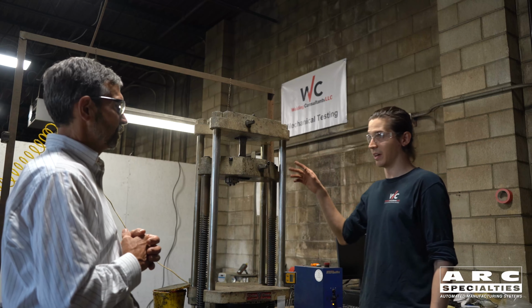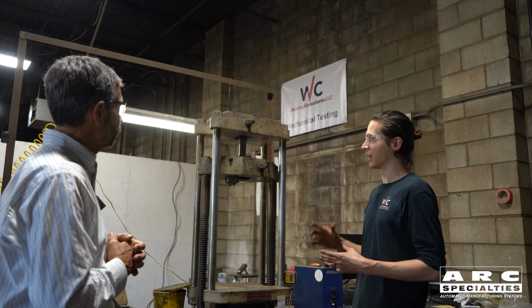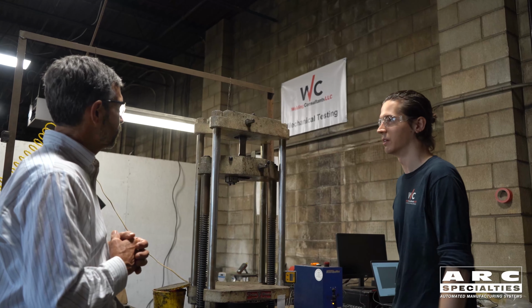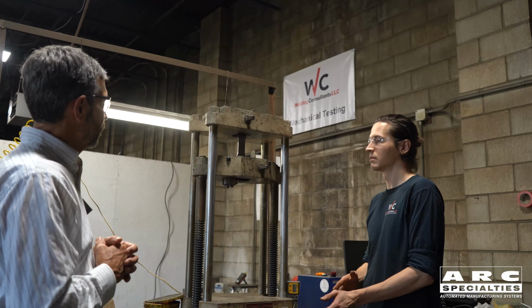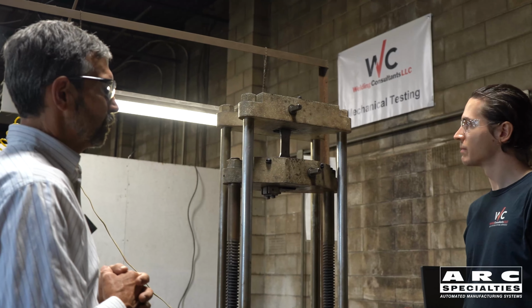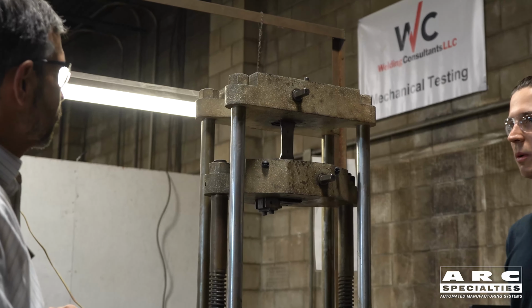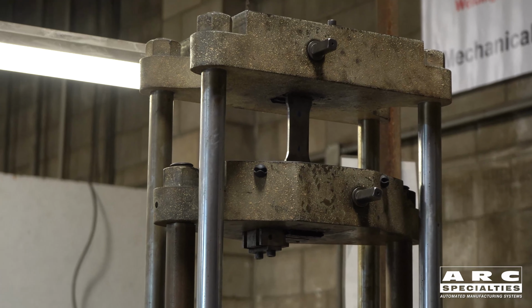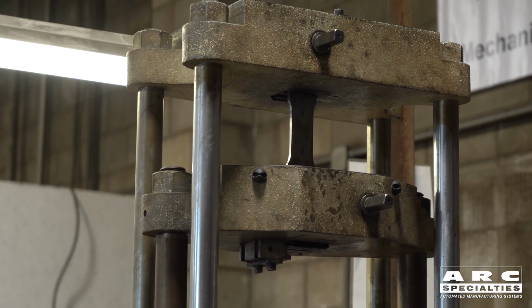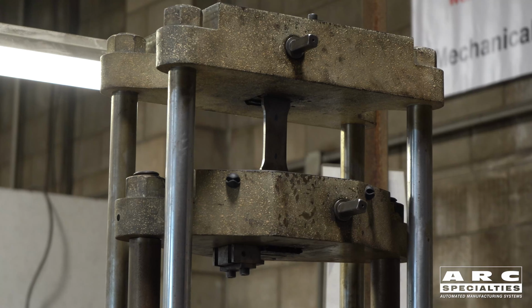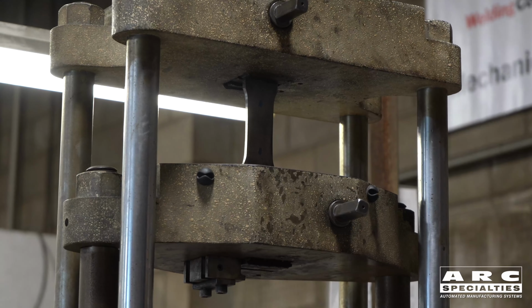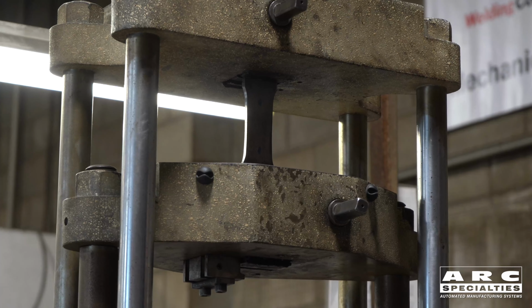Only 6/1000ths? Yes. Right here is where you see major elongation. It can be 1/4 inch or more. And that was over a 2-inch gauge length, or what's that? Yeah, 2-inch gauge length is what we measure across. But now I'm seeing stretching on the order of a 1/4 inch or more. Yeah, it's hard to tell at the moment, but this is definitely stretching by quite a bit. You can tell physically that is not 2 inches anymore between those two marks.